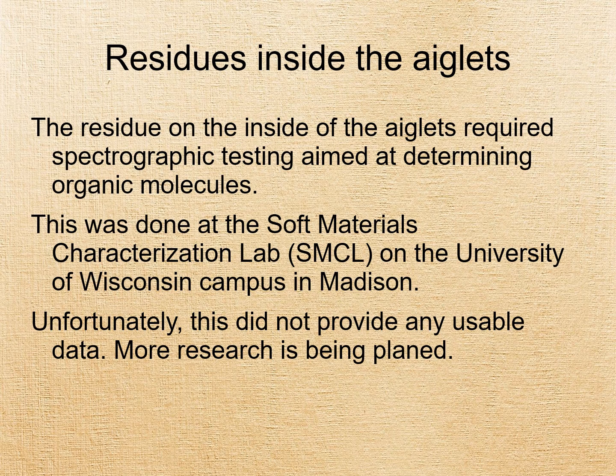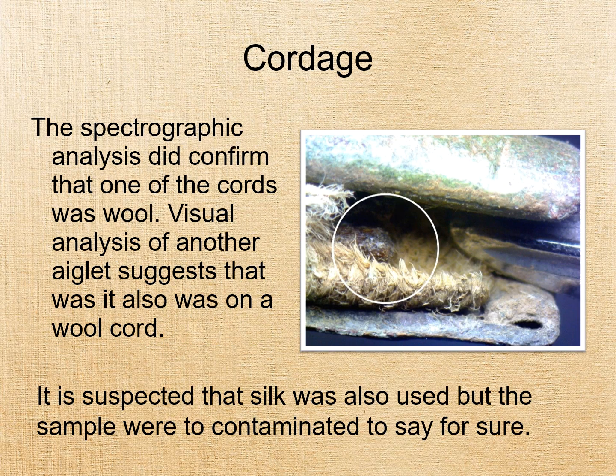ATR, attenuated total reflectance Fourier transform infrared spectroscopy, is a non-destructive, fast, and convenient method often requiring minimal sample preparation. With a micro ATR accessory, it is possible to use very small sample sizes, and the IR spectra can be measured directly from the sample surface. Micro ATR testing did tell us a little bit about the cords. I was not successful in determining the adhesives.